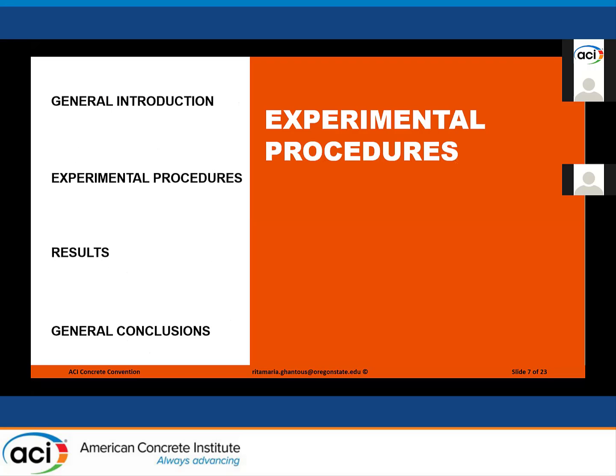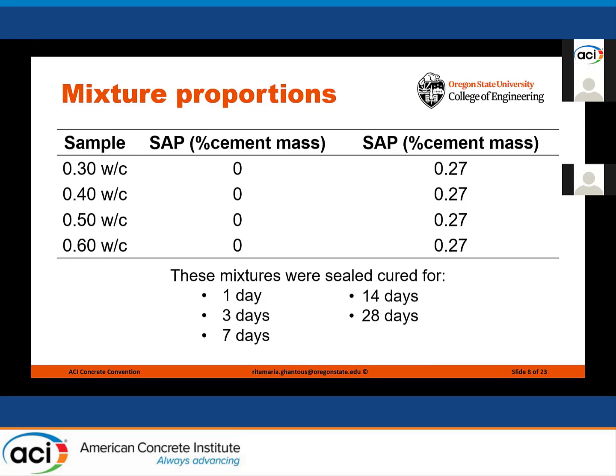So for the experimental procedures, we first start by preparing 8 different cement-based mixtures with varying water to cement ratio. So we have 4 different water to cement ratios, 0.3, 0.4, 0.5, and 0.6, with and without superabsorbent polymer. These mixtures were all sealed cured at 23 degrees Celsius for varying durations: 1 day, 3 days, 7 days, 14 days, and 28 days. After curing, they were immediately exposed to freezing and thawing cycles without any drying period. It's unlikely to be the case in the field, so results in this presentation should be viewed as a worst-case scenario.